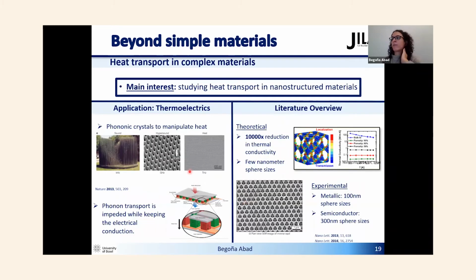Okay, the main interest of these materials was studying heat transport on these metalattices because these are phononic crystals, and this allows us to manipulate heat. So when you arrange two materials in a periodic manner, depending on the size of the period, you are able to manipulate sound or hypersound, or even if you go to sufficiently small periods, you're able to manipulate heat. And this is the case for these nanostructured materials.